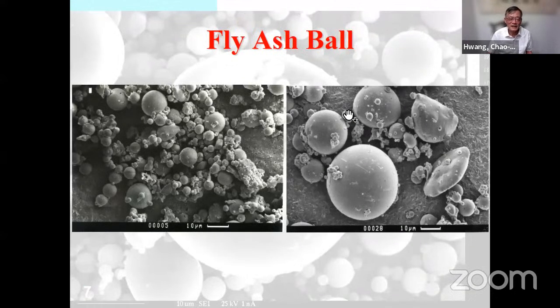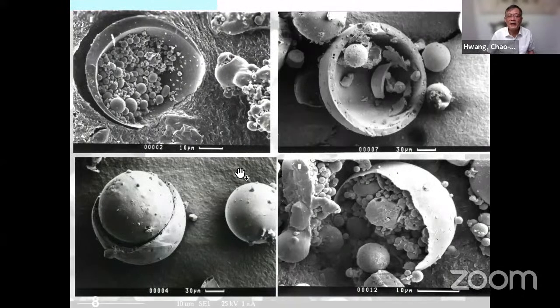Looking at the size, this is 10 micron here. The size can be 30 micron down to 1 or 2 micron, some particles are very, very small. The small particles of fly ash can be used as a fire-resistant material. In Taiwan, it has been used for high insulation materials. And those big spherical balls actually contain a lot of different sizes of fly ash particles. After you grind them, they can release a lot of very useful fly ash particles. That aids and reduces the amount of cement required.